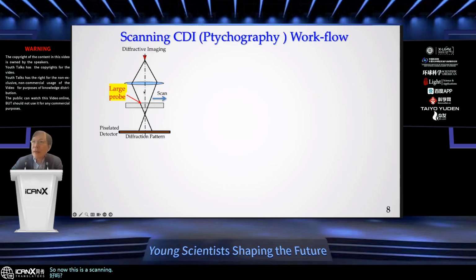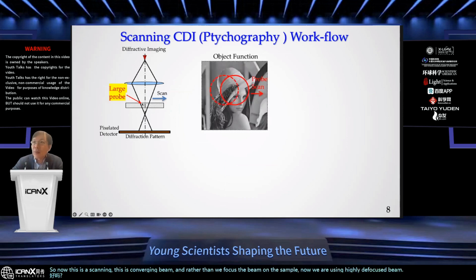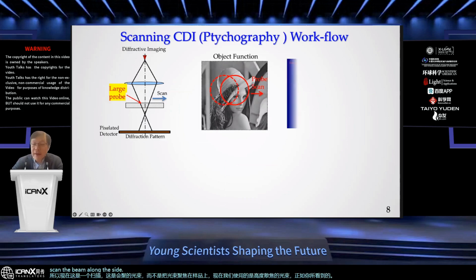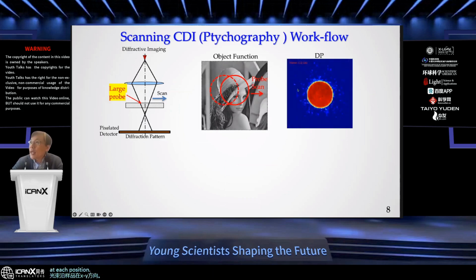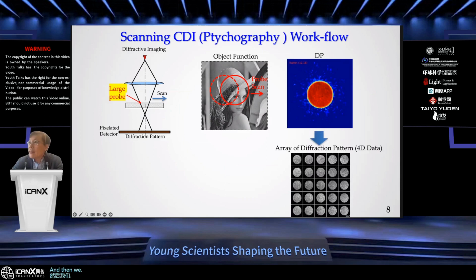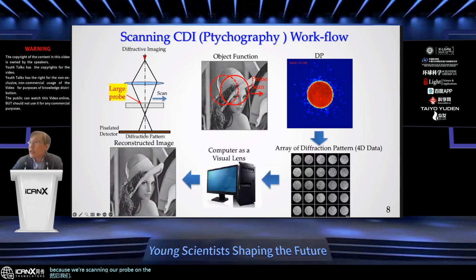Okay, so now this is a scanning. This is a converging beam, and rather than focusing the beam on the sample, now we are using a highly defocused beam, as you can see, and then we scan the beam along the sample in the XY direction. At each position, we take a diffraction pattern like this one. Because we scan our probe on the sample, at each position we have a diffraction pattern, and then we can form this 4-dimensional data, and then we feed this data into the computer algorithm. Hopefully, we can reconstruct the object that we have.